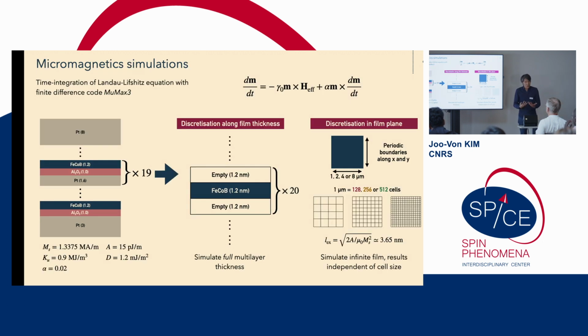And so we tried to model this through micromagnetics. So this is the kind of thing that I do. What we found to be very important was to model the full 20-layer repeat, because the dipolar interactions are quite important in such systems. Other groups have used effective medium theories to try to model what's going on, but we did the full stack with a number of different discretization schemes that I won't bore you with the details of.